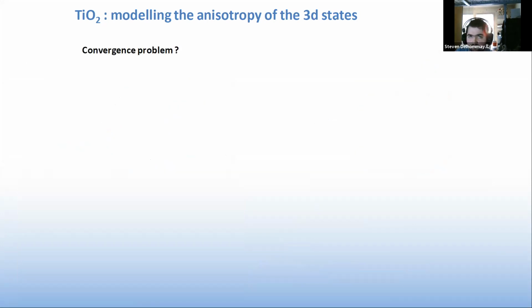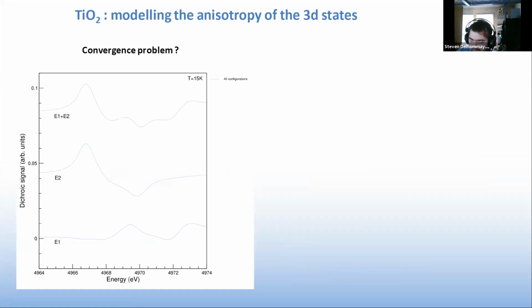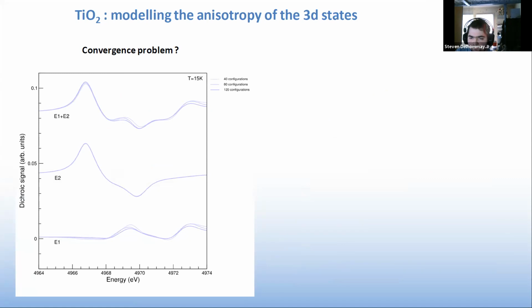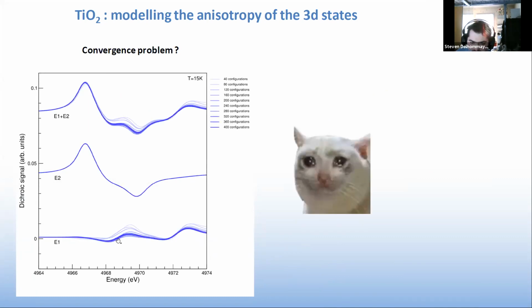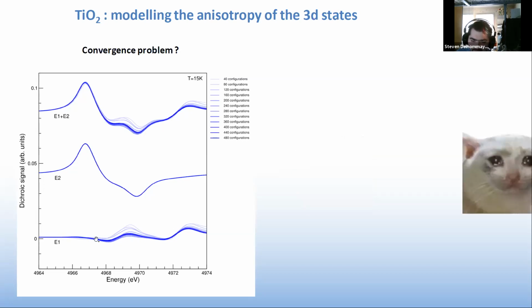The first idea is to think that it's a convergence problem, because as a matter of fact, all the spectra we get have a convergence that is a function of the number of configurations used. So we can check it. Here is the result we get for 40 configurations, for 80, for 120, etc., until 200. And here we're starting to get hope because the E1 signal is starting to go to zero little by little. But if we add more configurations, as the cat indicates here, we're not very happy because it seems to be converging to a non-zero signal. And as a matter of fact, when we add more and more configurations, the signal indeed converges to a non-zero contribution for the E1 contribution, which makes the cat go away in dismay.